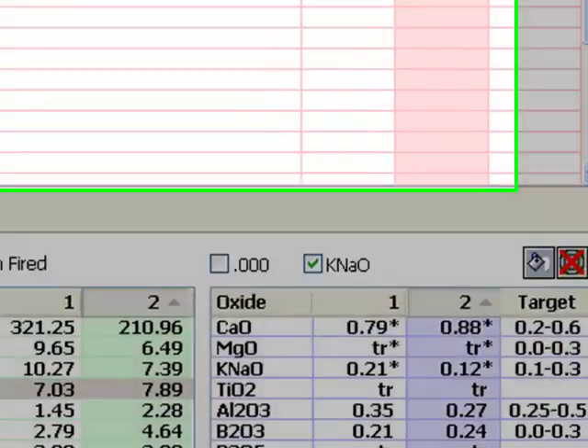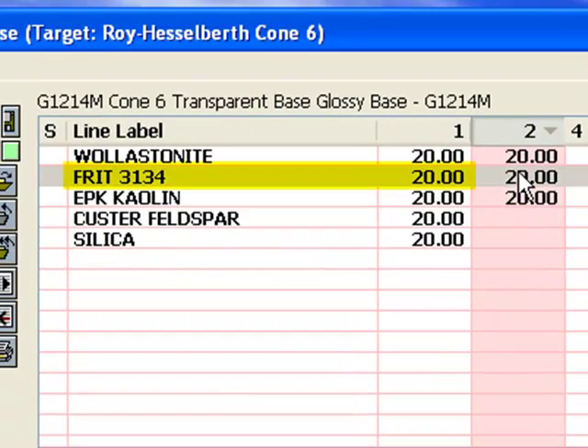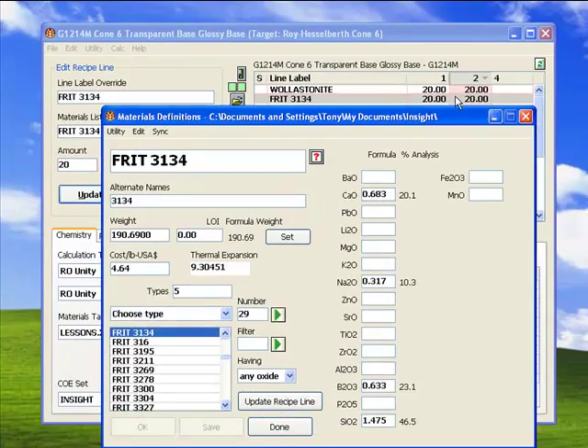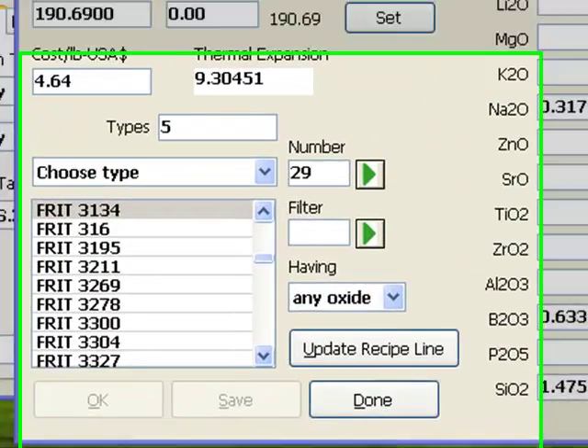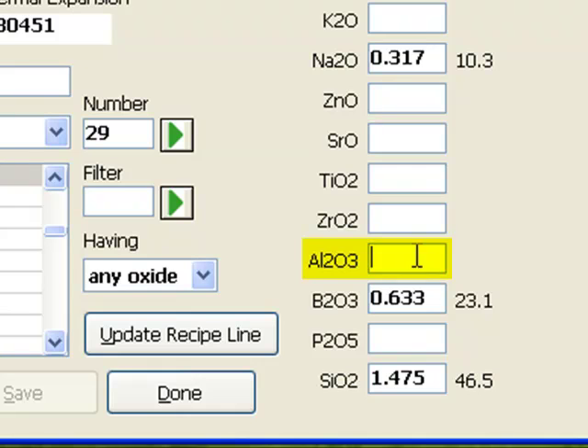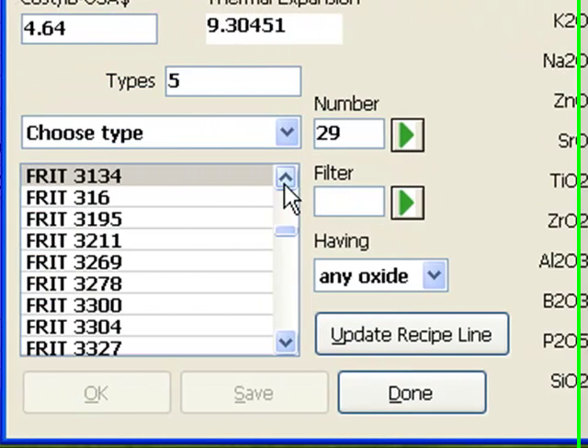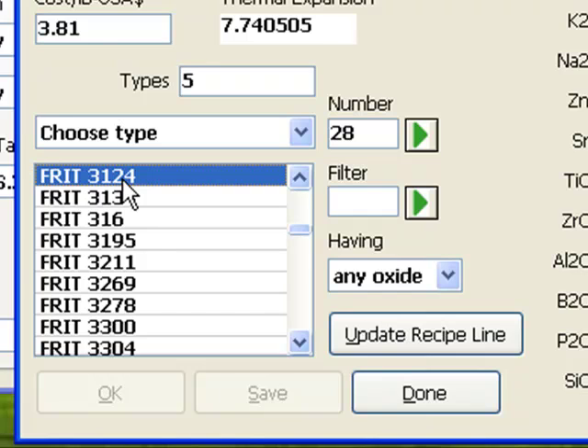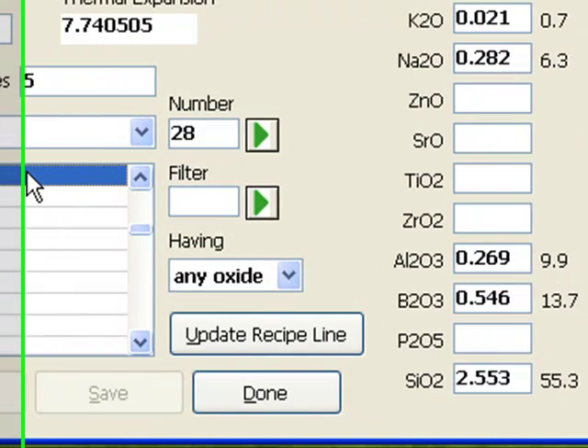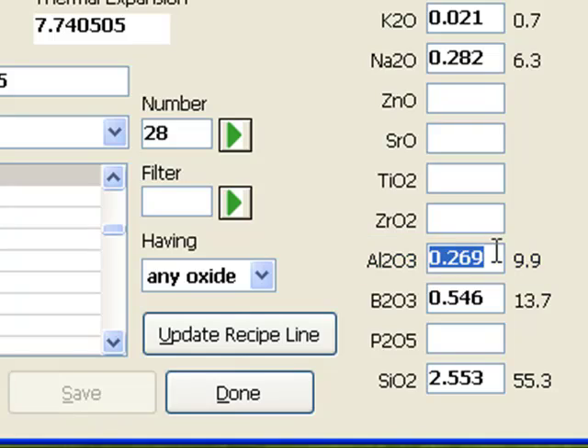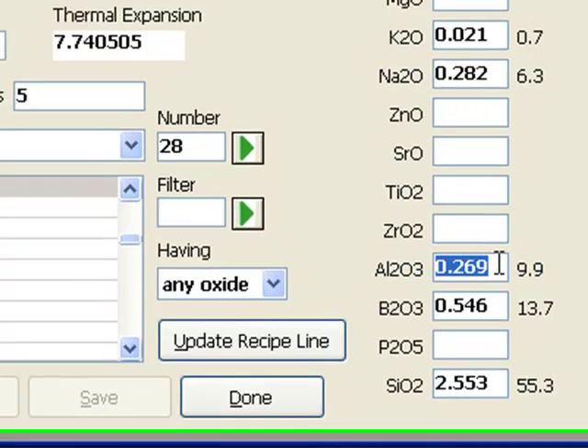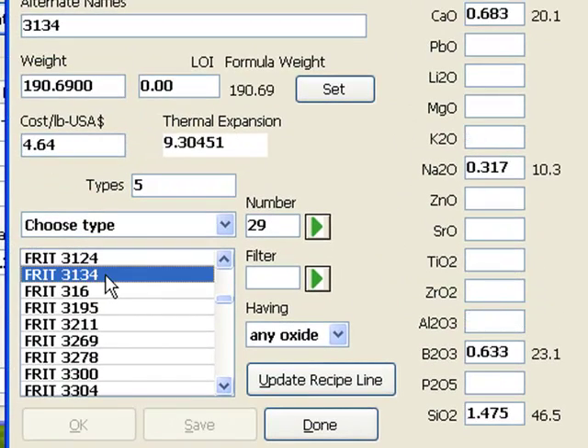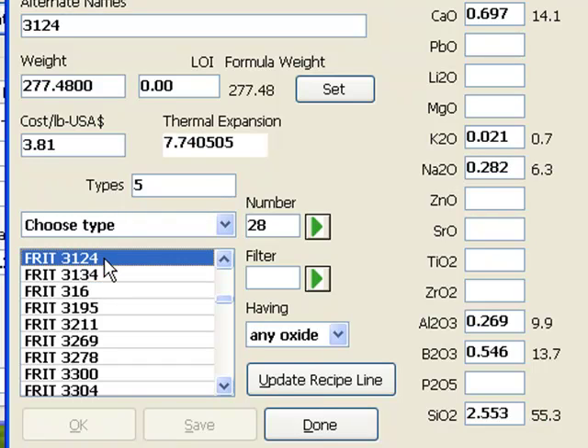Now I'll select the frit line and double-click it to open the materials dialog. Notice that this frit contains no Al2O3. I'll click frit 3124. It's just above frit 3134, so I need to scroll the list up. Notice that frit 3124 has significant Al2O3. It is interesting to note that if you add enough alumina to frit 3134 to equal the alumina in frit 3124, the overall chemistries are very similar. As you can see, using a frit with no alumina is a little illogical for making a matte glaze if it necessitates the use of too much clay to source alumina.